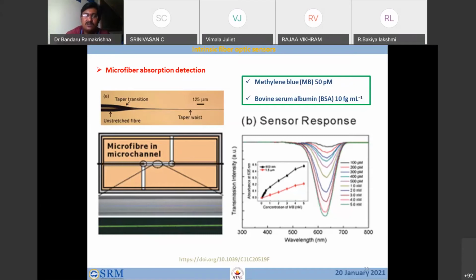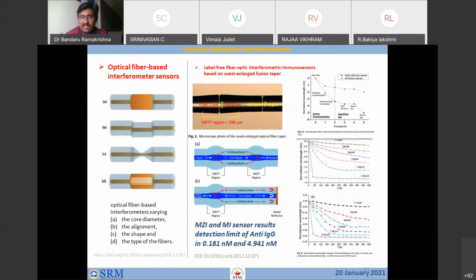People tried with tapered fiber. Some results are given here. And some other researchers have tried interferometric sensors. We talked about RI and evanescent wave sensors. Now it is interferometric sensors. Here it is Mach-Zehnder interferometry and Michelson interferometry. People have tried both. In these cases, you see antibody concentrations around 0.181 nanomolar and 4.941 nanomolar. However, in this experiment, they found that Mach-Zehnder interferometry is better than Michelson interferometry. So people have tried this, and biomolecular detection has happened with this.